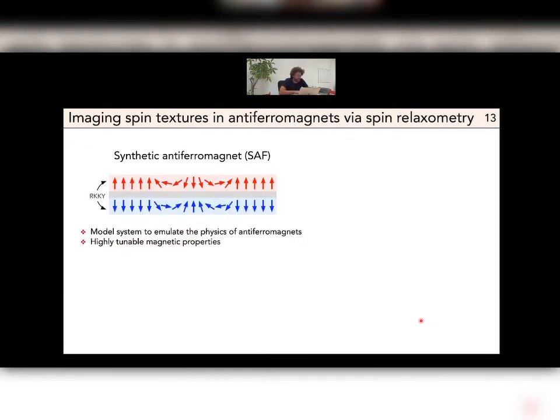And just to show perhaps a kind of proof of concept experiment, we decided to study synthetic antiferromagnets. So these are not intrinsic antiferromagnets, this is just two ferromagnetic layers that are coupled antiferromagnetically by a non-magnetic spacer. So this kind of system can be somehow considered as a model system that can be used to emulate the physics of antiferromagnets. But what is really nice with synthetic antiferromagnets is that we can really tune their magnetic properties by changing the thickness of the different layers.